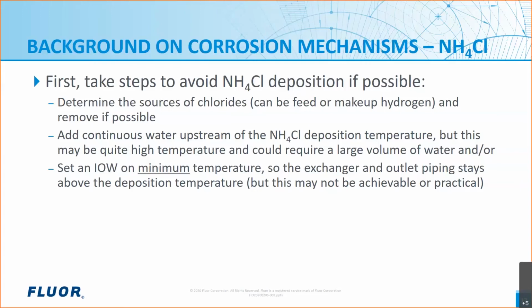And then another option is to set an IOW on the minimum temperature. So say we're worried about that last shell and tube exchanger, maybe we design that exchanger or have a bypass around it on the other side so that the effluent stays at a minimum temperature at the outlet of it, so that it's staying still above the ammonium chloride deposition temperature. This sometimes works if you're borderline, very close to the deposition temperature, and this will ensure you do stay above it. But if you're far below the deposition temperature, this just wouldn't be achievable or practical.